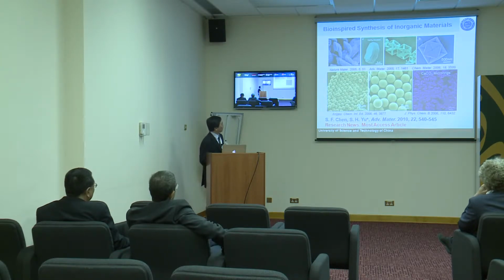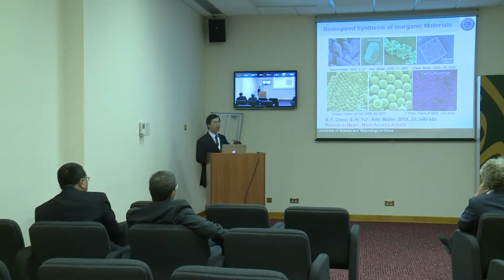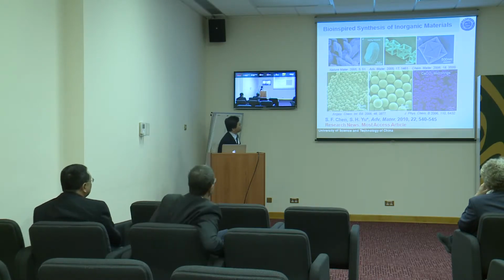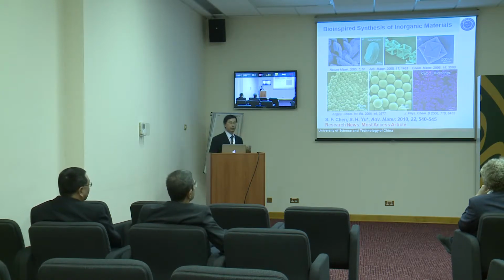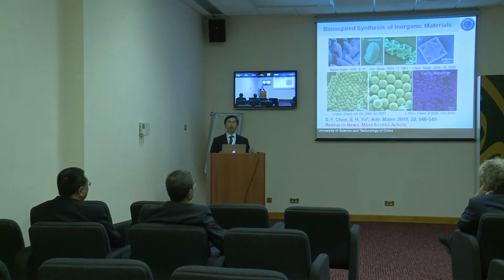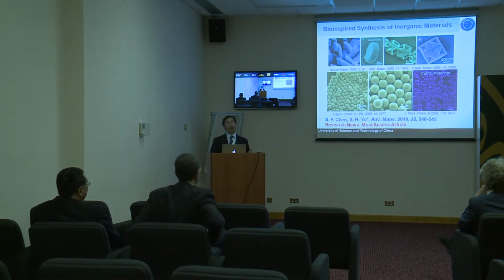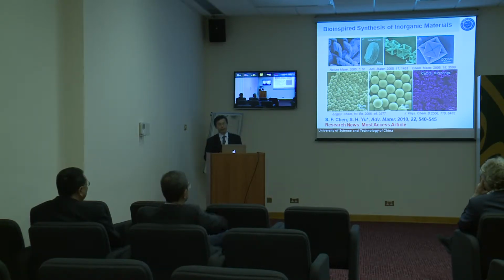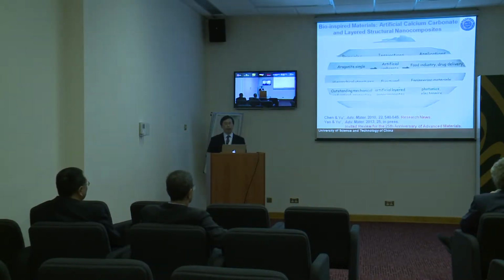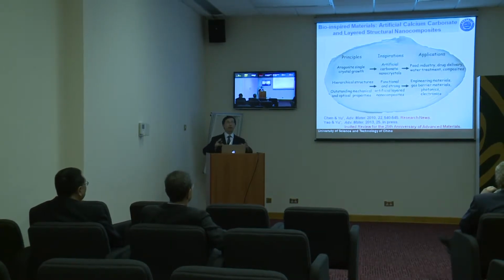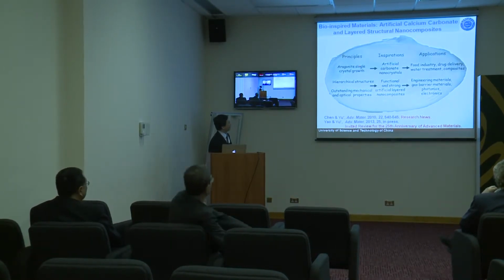We can synthesize these very uniform micro-sized calcium carbonate spheres, and also you can get these multi-layer pancake structures, and you also can get this very unique ring-like structure, micro-rings. So that means polymers with a similar functionality as biomolecules can control the growth process of very different inorganic materials. So then we consider how we can build up these big guys.